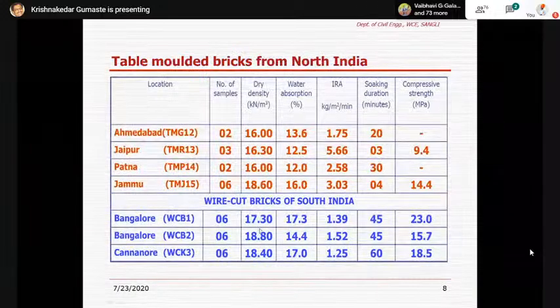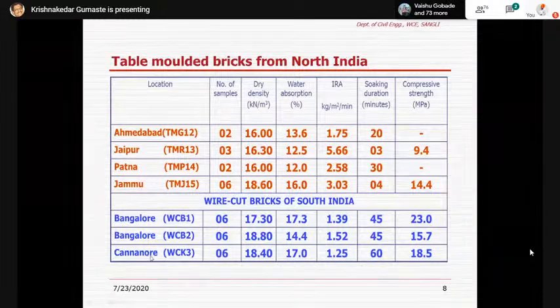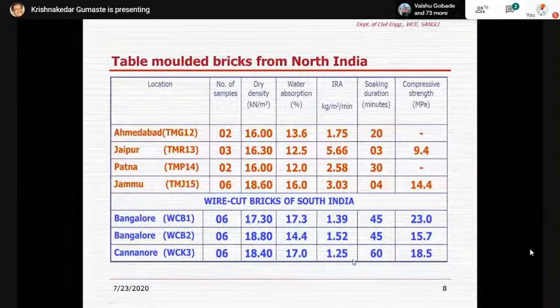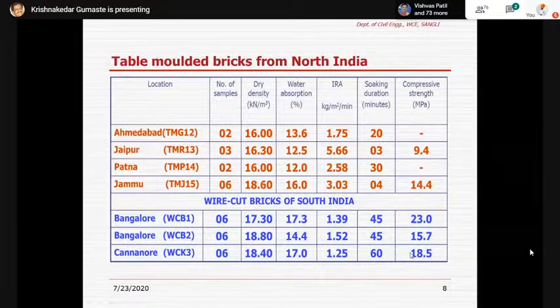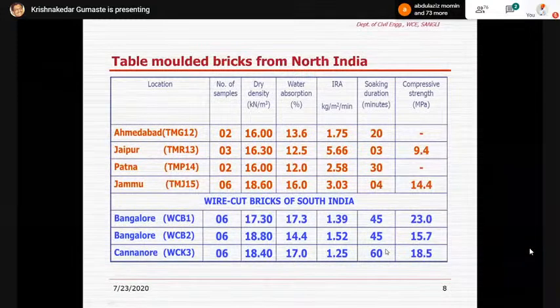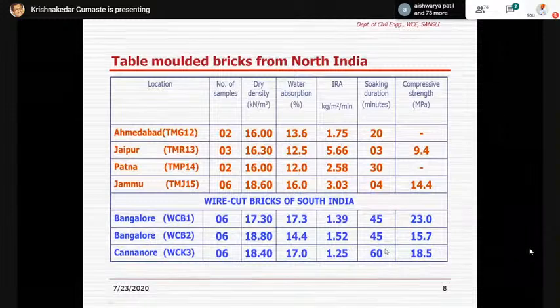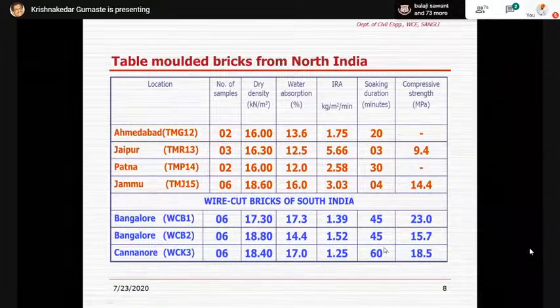The wire-cut bricks of southern peninsular regions, that is from Bangalore and Kerala, Kannur and Udagamandalam, you can see the compressive strengths are much, much higher. And the soaking duration of such bricks becomes higher because the water absorption is lower. These wire-cut bricks are basically to be soaked in water for partial saturation for up to 1 hour, about 45 to 60 minutes. That is a summary of all these, although I take a lot of time in explaining this, but today it is not the context of just discussing the material.